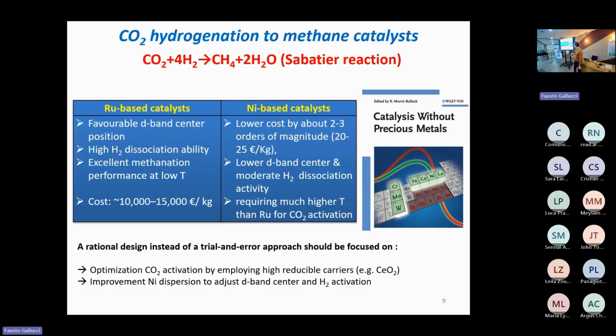On the other hand, transition metals like nickel exhibit, of course, a much lower cost, by about 2 to 3 orders of magnitude lower compared to ruthenium, but also show a lower d-band center and a moderate hydrogen dissociation ability, thus requiring much higher temperatures than ruthenium in order to achieve the same conversion levels. Thus, in the case of CO2 methanation over nickel-based catalysts, a rational design approach should be focused on the optimization of CO2 activation by employing, for example, as I will show you later, highly reducible supporting materials, and by the improvement of nickel dispersion and metal support interactions in order to adjust the d-band center and the hydrogen spillover.